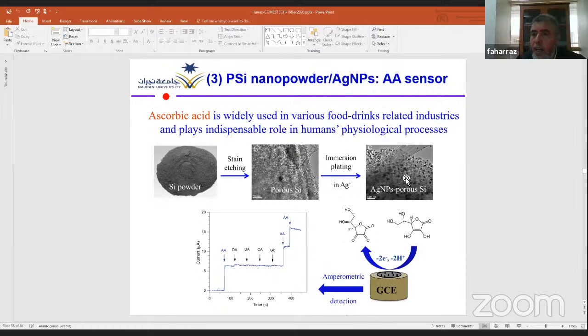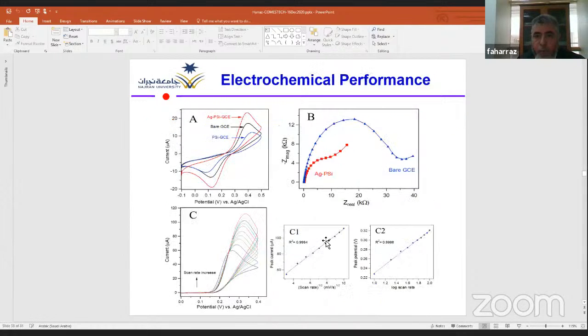We use this powder, and using some binder, we can fabricate a paste and cast it onto a glassy carbon electrode. We use this interesting structure as a modified working electrode to make a sensor for ascorbic acid using electrochemistry, especially the amperometric technique. This is the electrochemical performance of our sensing material modified electrode. There is great enhancement in the electrochemical activity of our modified electrode.